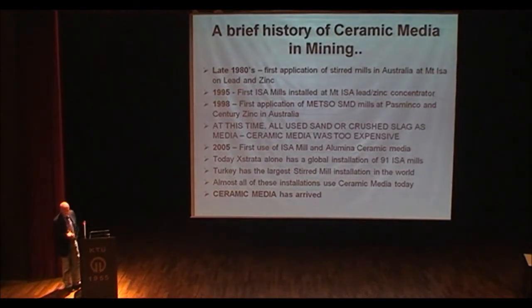So they were using sand or crushed slag. The problem with that was it did work, but the sand was soft and you ended up with a lot of useless slimes that went through with your process, either into flotation or leaching. So there was a need to get something better.